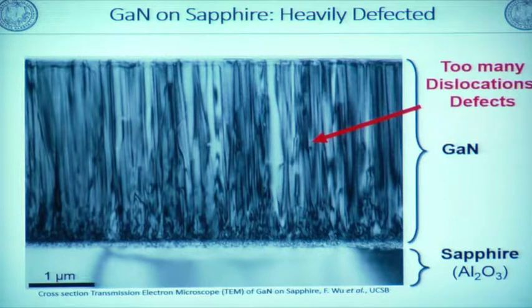In this scale, this dark line should be 0 to make highly efficient LEDs. It was common sense in the 70s and 80s. In order to make efficient and reliable LEDs, this line defect should be 0 in this scale. You can see this is terrible. It's a crappy material. So that's the reason in the 80s and 70s, basically nobody tried this material, because this is the biggest problem. In the case of zinc selenide, almost nothing. It's a beautiful crystal.